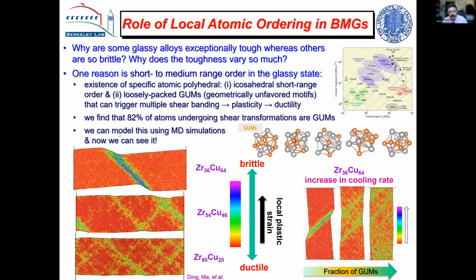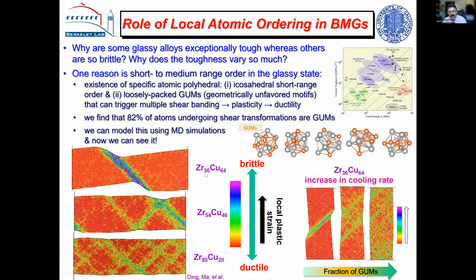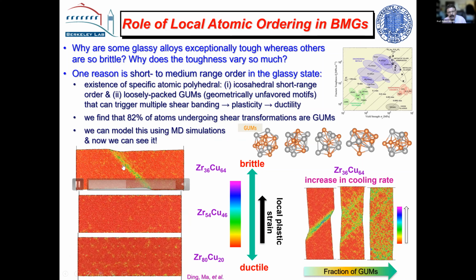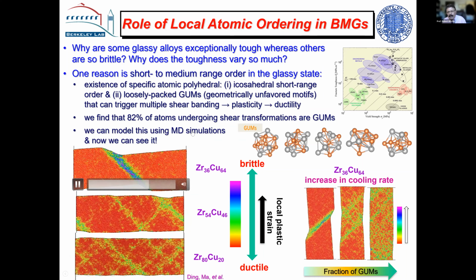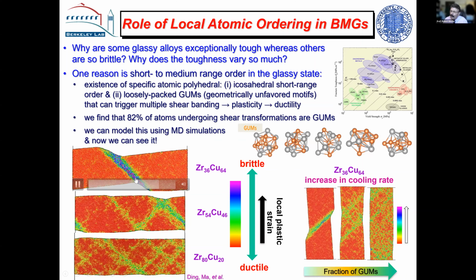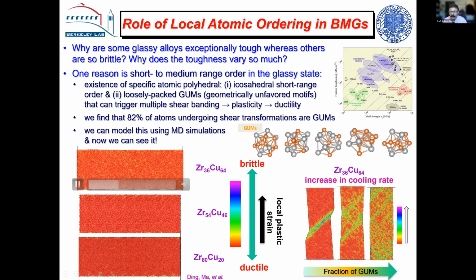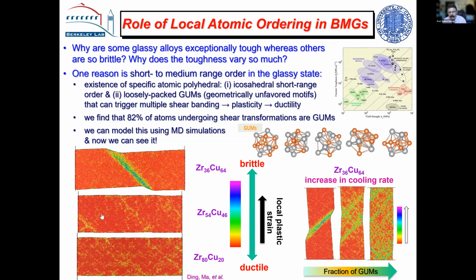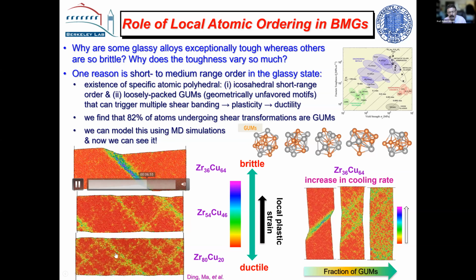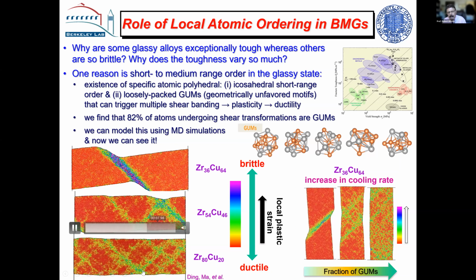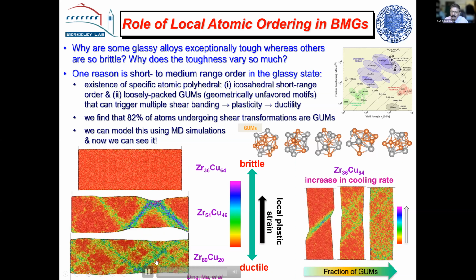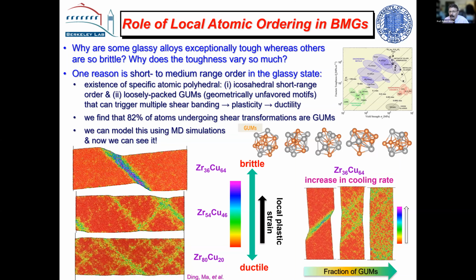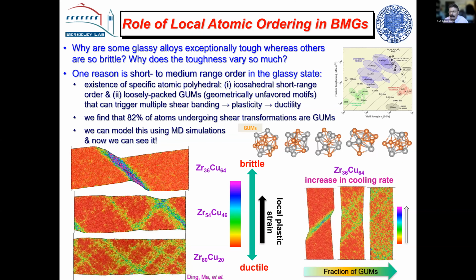These are basically MD simulations. In this particular composition, they're all zirconium copper. You just have a situation where you don't have many GUMs, and so you just get shear bands in one place, and you get a degradation of the properties quite considerably. It just necks down to nothing. But if you can distribute them throughout the structure, you can see you get multiple shear bands, and that leads to a degree of plasticity, because the GUMs are what lead to the shear bands, which lead to the plasticity.